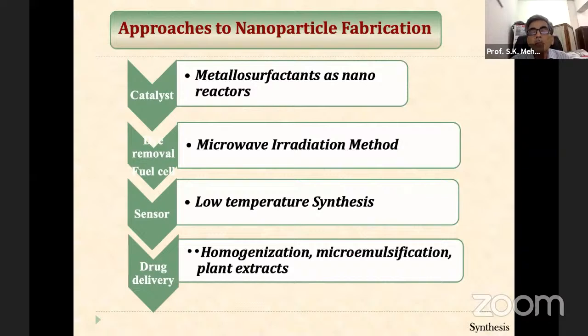And the second example I can take: this microwave irradiation method is very, very effective. And we created a lot of nanoparticles where we used the microwave irradiation method. Then low temperature synthesis, homogenization, microemulsion using plant extracts we also tried, and for different purposes we can use them: for drug delivery, as catalyst, for dye removal. A lot of work is being done on dye removal, fuel cells, and as sensors.